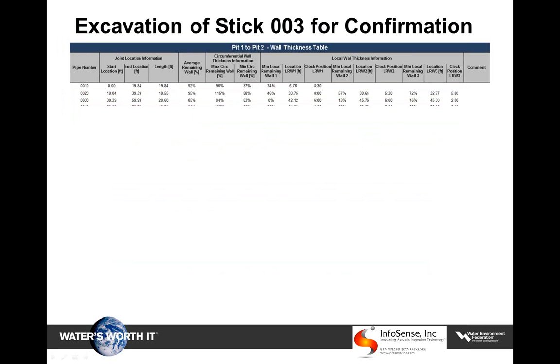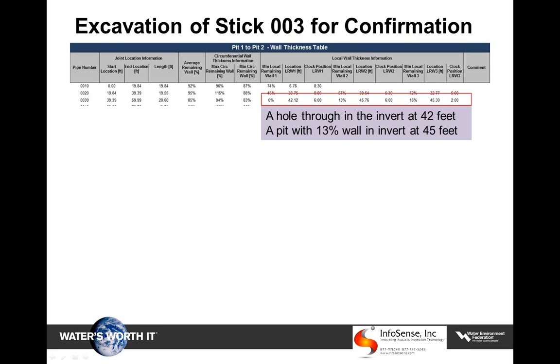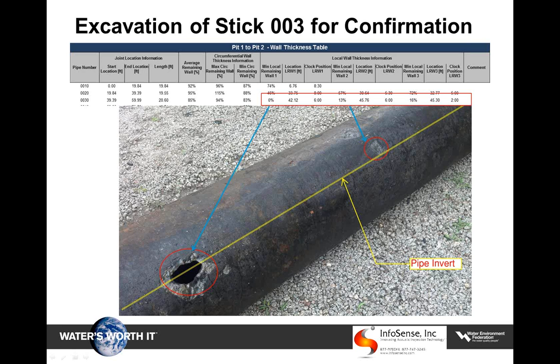So we went to stick number 3, which had a hole in it in the invert, and a pit with 13% wall remaining about 3 feet away from that hole. And we dug it up, pulled it out, and here's what we found. Exactly where the tool said it was, there was a hole in the invert, and 3 feet away was a deep pit. So with this level of confidence in the data, the client went ahead and replaced the first 650 feet of damaged pipe with a PVC C900 and is keeping the other 3,900 feet in service.